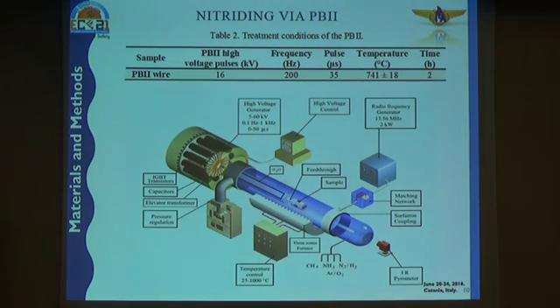We have a wire, now we have to make the treatment, the plasma-based treatment. Here is the setup that we used. This is the chamber where we are going to implant the plasma. The sample stays here. Here are the treatment conditions of PBII. We use high voltage pulses, 16 kilovolts, frequency of 200 hertz, pulses of 35 microseconds, temperature of treatment 741 degrees Celsius for 2 hours.